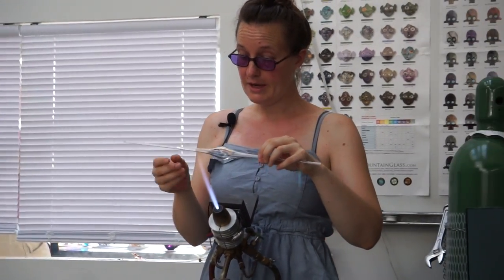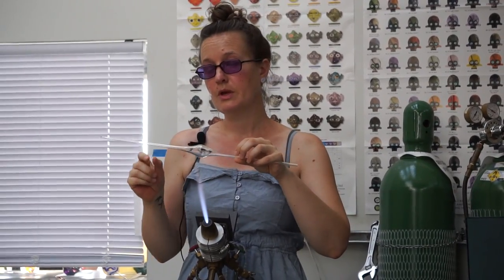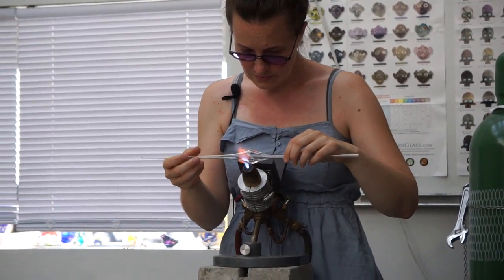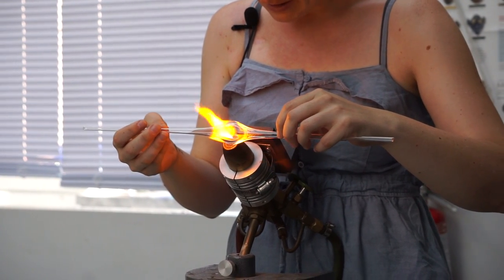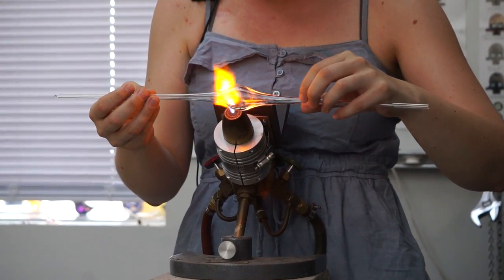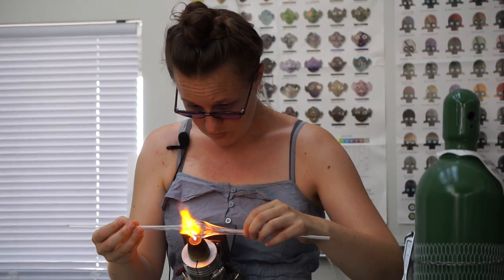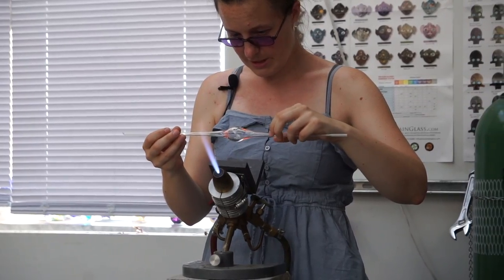I'm gonna get in here and make two little constrictions on either side. If you're familiar with the hot shop, this is like my jack line. I'm making a little constriction on either side of the bubble so the flame doesn't lick over into the thin skinny little handle. I'm pulling really gently and letting the glass condense down so it's a little bit thicker right there, so if the flame hits it it won't start wobbling. Then I'll let that cool on center.